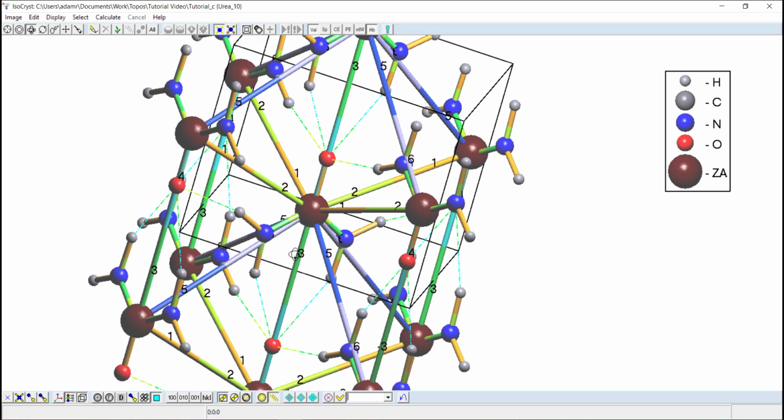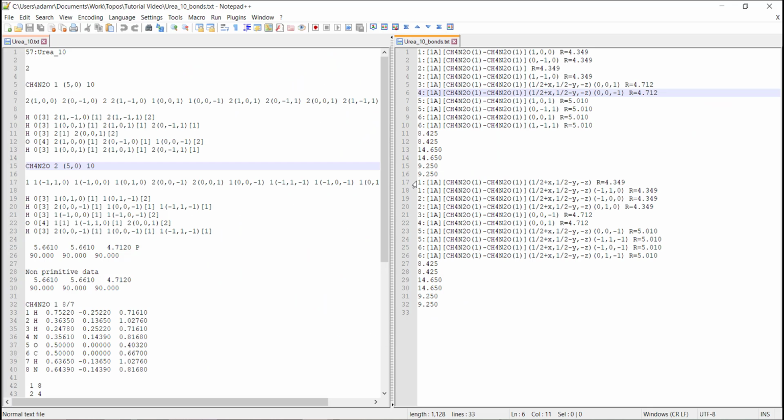This may help us to make a decision about what energies to assign to each of these species. As I said before, we still need to consider the interactions with solvent. As we're going from solvent to crystal, we're calculating free energies of crystallization, so just because the bonds are stronger doesn't necessarily mean that they'll have higher free energies of crystallization. We can also then turn on the van der Waals interactions, and you can see which species those correspond to. It's a really useful way of finding out what your interactions in your net.txt or your bonds file correspond to. So we now know that 3 and 4 are pairs of hydrogen bonds, and 1 and 2 also have one hydrogen bond, whereas the rest of the interactions are van der Waals based.